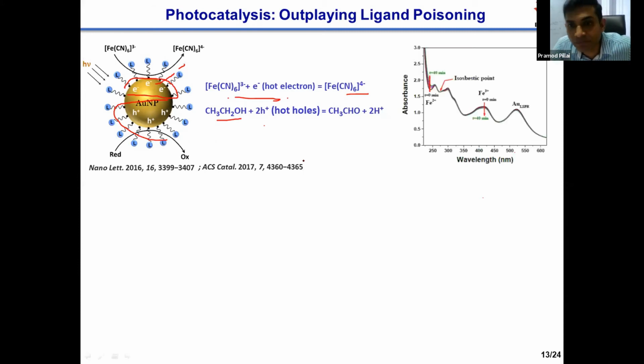So when we started this project, this was the best data which was available in the literature. So what you see here is the absorption of the gold nanoparticle, and this is the absorption of Fe3+. So when the reduction is happening, you can see that there is a very, very negligible decrease in the absorption band. And based on this decrease, they have come up with an electron transfer theory. So we thought that let's try to use our hypothesis here.